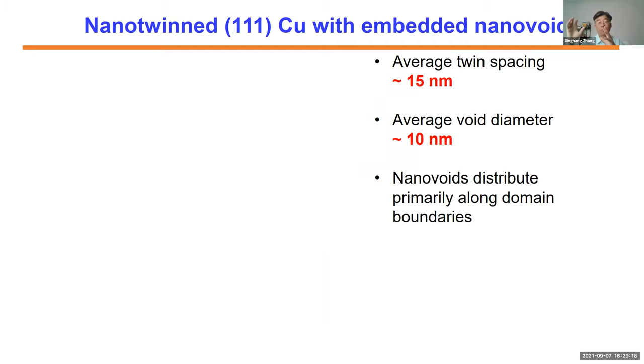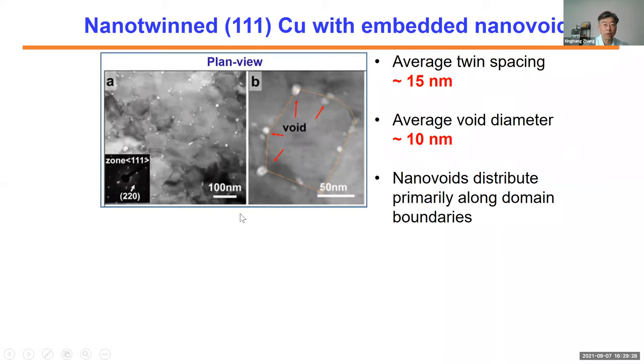And so now we switch from aluminum to copper. Copper is an interesting FCC metal. It's a very good model system. We started by looking at nanotwinned 111 texture copper. So this is our sputtered copper film. From plan view, you see single-crystal-like diffraction, but there's a bunch of nano voids in this copper.